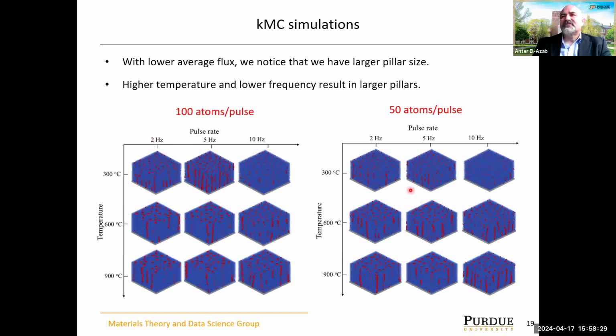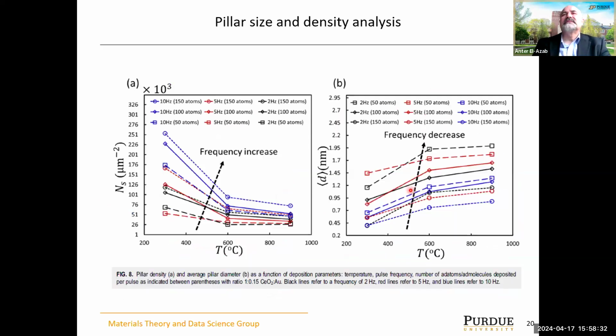This doesn't show much as far as a conclusion, but these figures here summarize the data that you show on that figure of the morphology. Density as a function of temperature for various rep rates in here, and they are plotted for pulse magnitudes of 150 atoms, 100 atoms, and 50 atoms. And then the pillar size on average here as a function of temperature, again, for these deposition parameters. So this is a lot of data condensed on one figure.